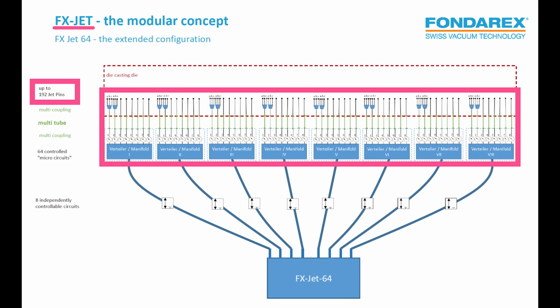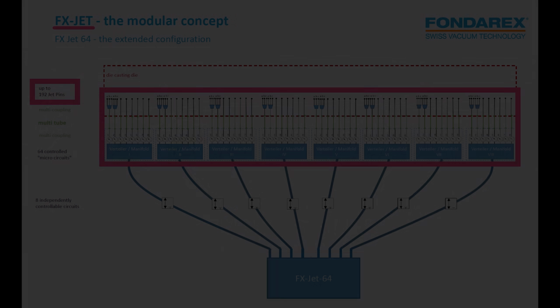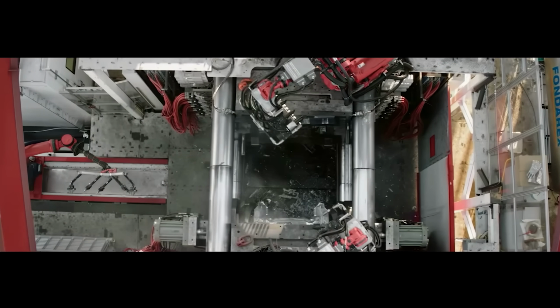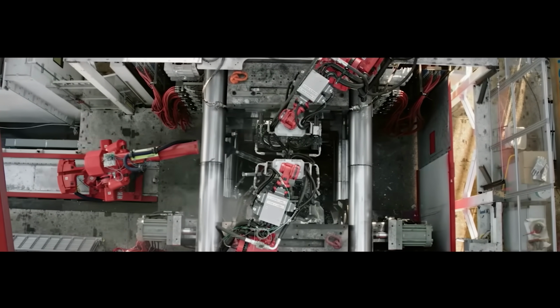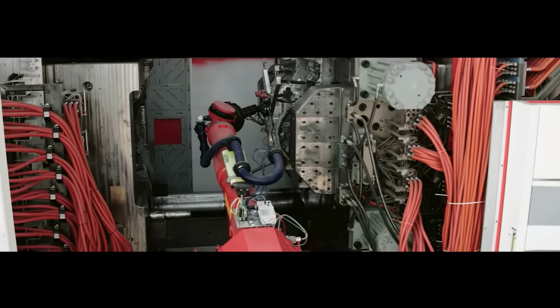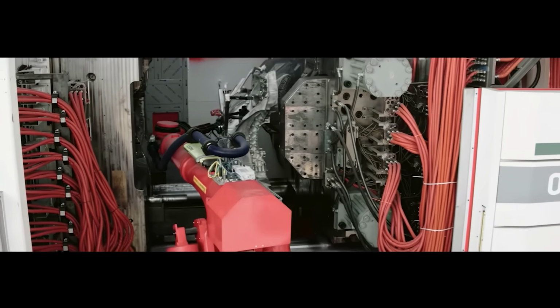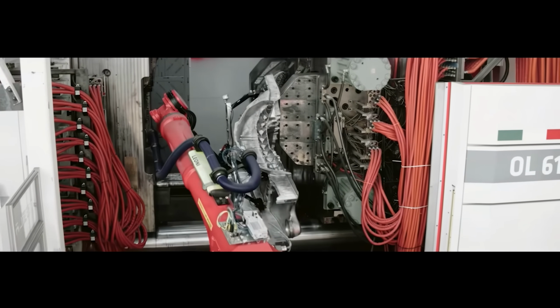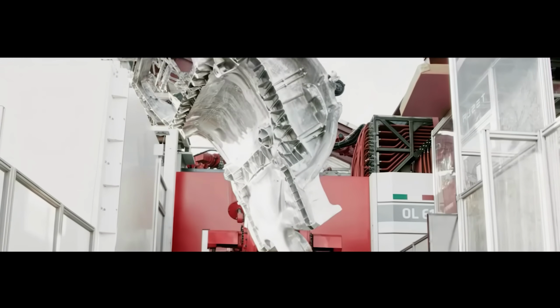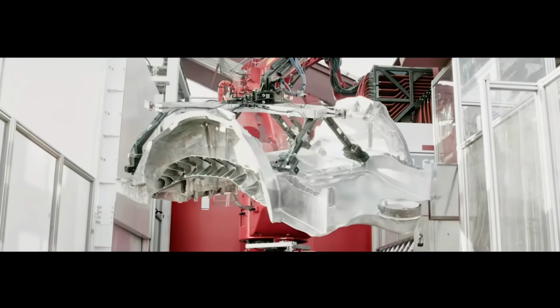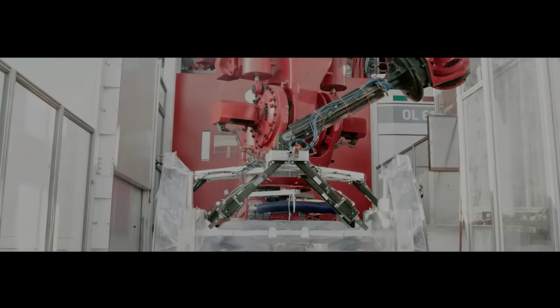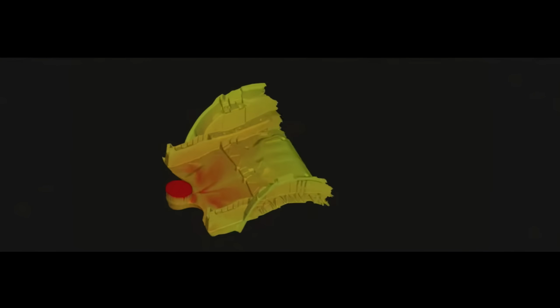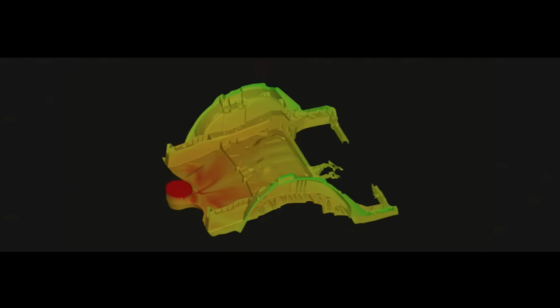Adding up to 192 evaporative cooling injector pins adds another layer of complexity on top of that. Furthermore, with larger parts due to gigacasting, it becomes increasingly difficult to model that turbulent flow as well as manage the casting process, because with larger parts comes greater thickness variability throughout the part, meaning larger temperature gradients. That matters because every part of the casting has to cool at the right rate to avoid shrinkage and part